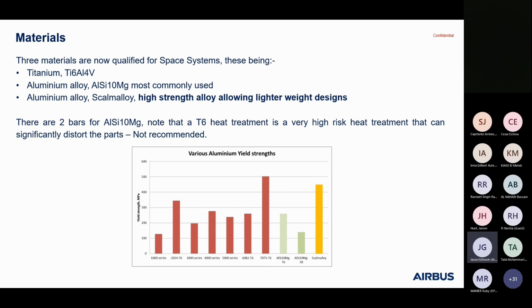And basically our fallback position is we do not heat treat aluminium silicon 10 to a T6 condition. We use it in the stress relief condition. And when you look at the yield strength of the stress relief condition, it's about as poor as a pure aluminium 1000 series, so really low strength. Now, one of the winning themes of Scalmalloy is that to get your high strength, it requires a stress relief, which is 325 degrees C for 4 hours and an air cool. Thus, you're not introducing this quenching, and you get a yield strength of over 450 design allowable.